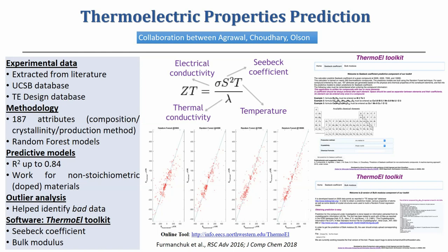So we found that our model was performing very badly in some cases. The postdoc who worked on it couldn't really stop herself. She went back to the papers and found what was going on. We found that in many of the cases where the model had failed, the data collection was erroneous. Seebeck coefficient is a polar quantity, so sometimes the sign was missing. Sometimes the magnitude was wrong. It was some other figure taken from the paper.